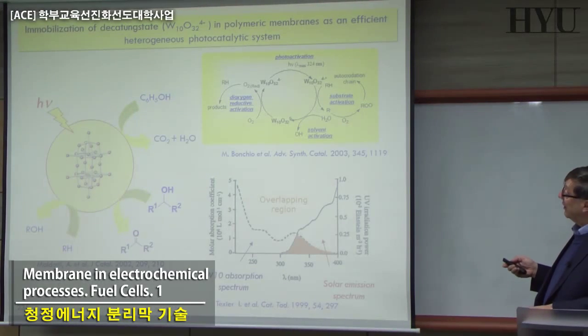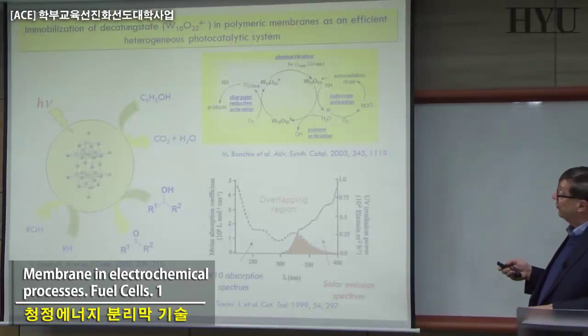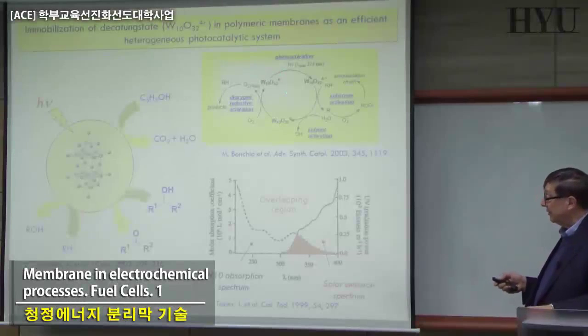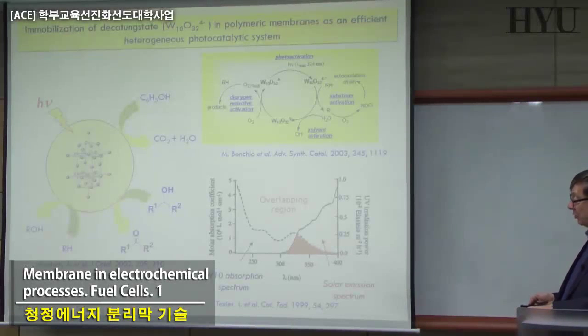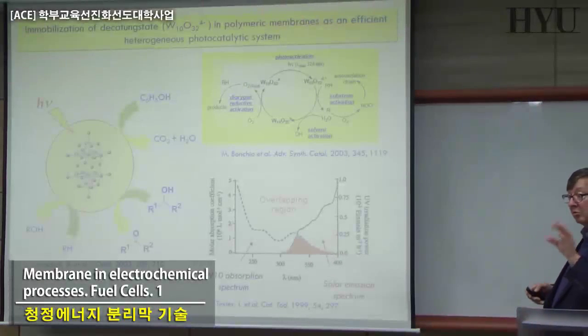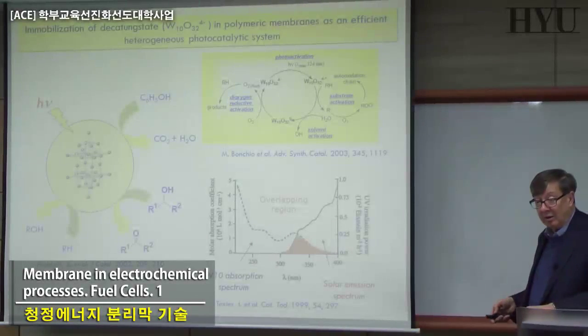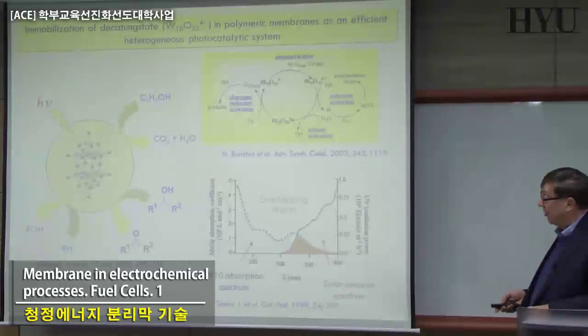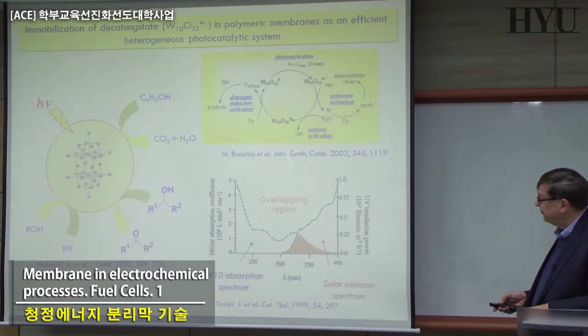This is a typical example of immobilization of one of these compounds, a decatungstate, in polymeric membranes as an efficient heterogeneous photocatalytic system. What is important is that the specific activity of the catalyst overlaps the area in which there is the solar emission. That means you don't need to use any lamp, etc. You can use the solar emission to activate your catalyst. And this is one of the areas in which this photocatalyst can be quite interesting.